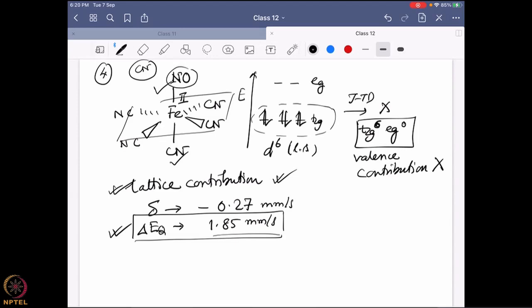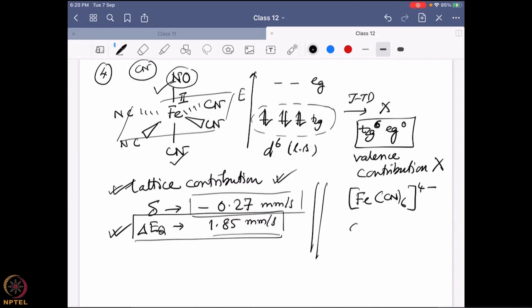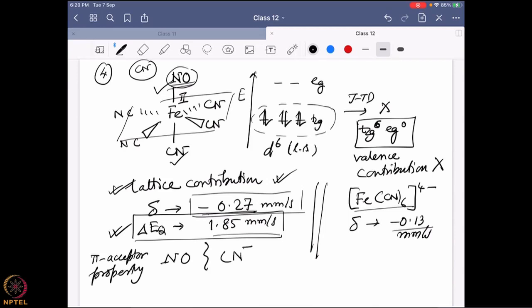Okay. Now, this value of delta equal to minus 0.27 is measured at the same condition where Fe(CN)6 4 minus is measured at delta equal to minus 0.13 millimeter per second. So iron with all cyanides is minus 0.13, iron with 5 cyanides and 1 nitrosyl is minus 0.27. So what can you comment on the pi acceptor property, a comparison between nitrosyl and cyanide, if we consider these delta values? You can see the delta value over here is more negative for the nitrosyl group containing system.